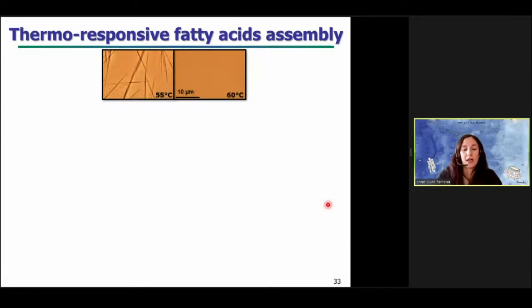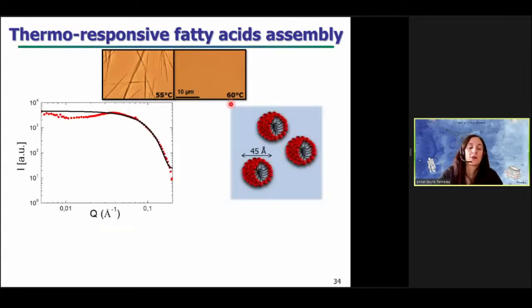Then we followed the response of these tubes as a function of the temperature. And what we observe by optical microscopy is tubes that appear as rods, here in black. We observe tubes until 55 degrees, but exactly at 60 degrees for this system, we don't see any more tubes, and the solution is completely isotropic. So again, we use small angle neutron scattering experiments, and here you can see the scattering curve at 60 degrees in red.